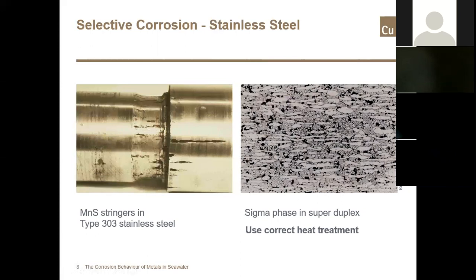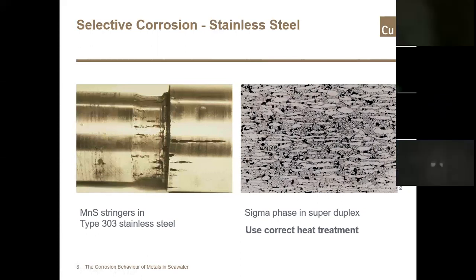it's a stainless steel. It's a free machining stainless steel, grade 303. But no consideration has been made for corrosion resistance, and this particular grade uses sulfur as a chip breaker, and this forms a manganese sulfide within the microstructure, and that phase is selectively corroded and eaten away, and even would be in normal tap water.